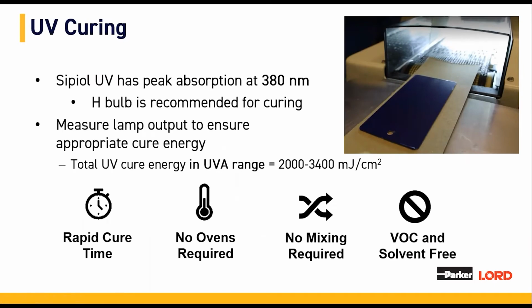Sipiol UV has peak absorption at 380 nanometers. We recommend curing with an H bulb and can work with you in selecting the appropriate equipment. It is important to measure the UV lamp output to ensure the appropriate energy is achieved. Energy output can be measured with a radiometer.